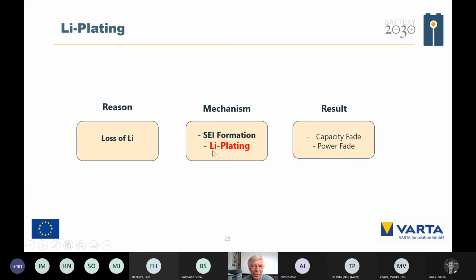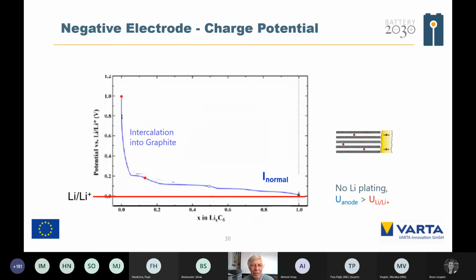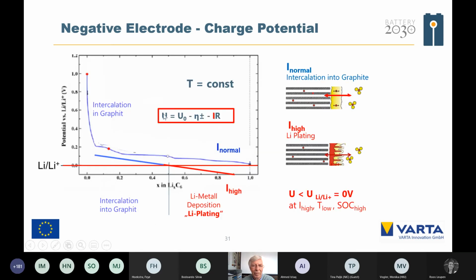The second mechanism for the loss of lithium is the lithium plating. If you are looking at that discharge charge curve of graphite, that is intercalation, you are always, if you have a normal discharge charge current, at a potential higher than the lithium potential. So you have no plating or lithium deposition as long as your anode potential is higher than the potential of the lithium electrode. But you know, via that equation, if you have a high current, then your charge potential is decreasing, like in that case. Here we have a normal charge current, and here we have a strong charge current. So the curve is going that way.